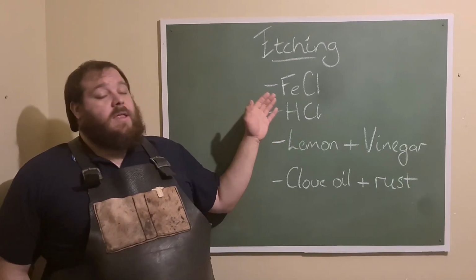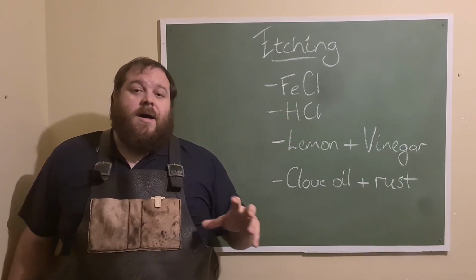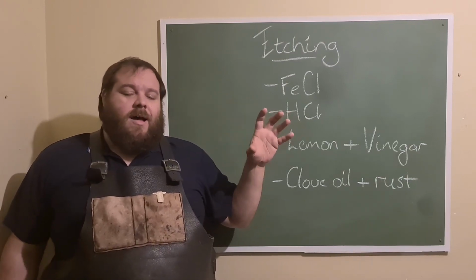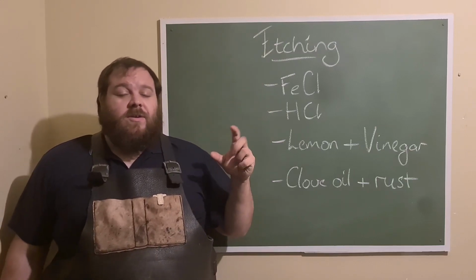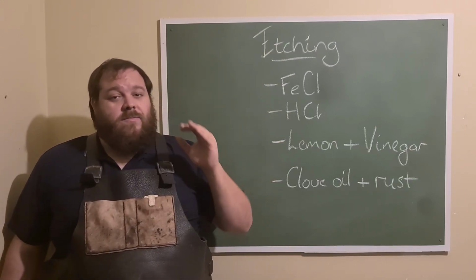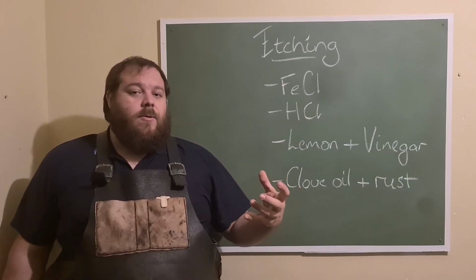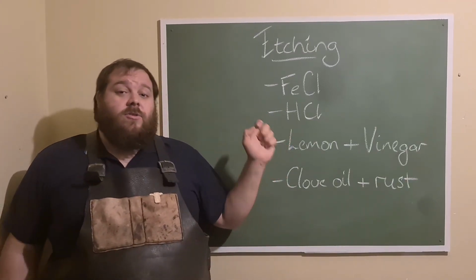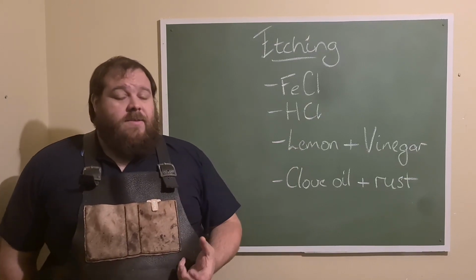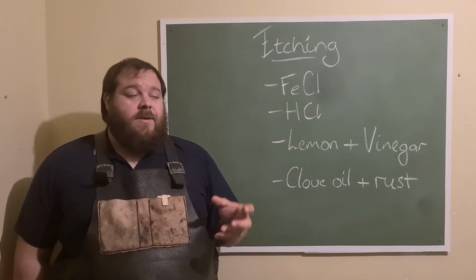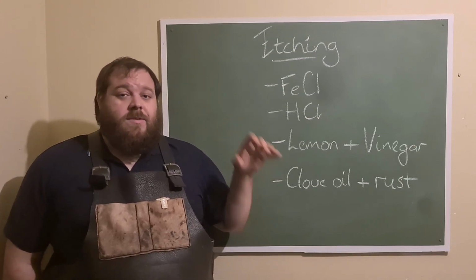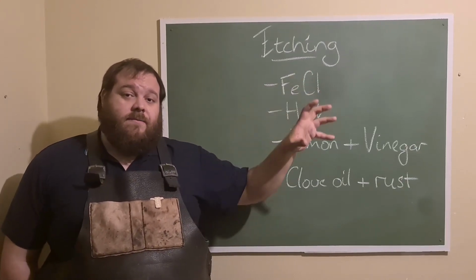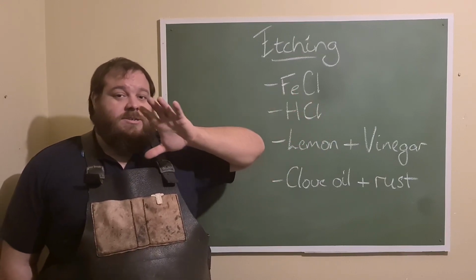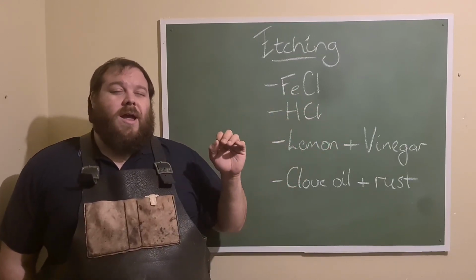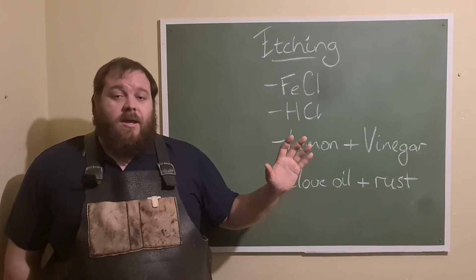But the other thing that ferric chloride does is it darkens the martensitic portion and leaves the unhardened portion gray. So it can give you a really nice contrast, especially if you're doing just a straight line Hamon. It's a really nice way to accentuate that Hamon. The other one is hydrochloric acid. Again, very aggressive, not as aggressive as ferric chloride, funnily enough, but what it doesn't do is create that juxtaposition between martensite and ferrite. It will end up with just gray with the Hamon, but it will create a more satiny color than a polished finish.